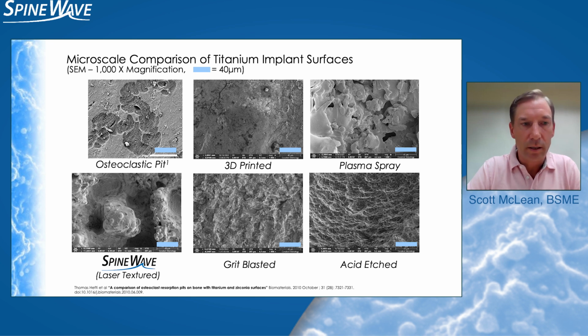And you can see in the bottom left that we're looking at the Testa Nano surface with the pits and pores that are roughly 50 to 100 microns in size, and how that compares nicely to the diameter of the osteoclastic pit. And again, we have much deeper pits and pores, and that is by design. The competitive implants, the 3D printed, plasma spray, grit blasted, and acid etched, you can see all have different levels of roughness, all in very random pattern, and you know that there's really no organized structure to the features.